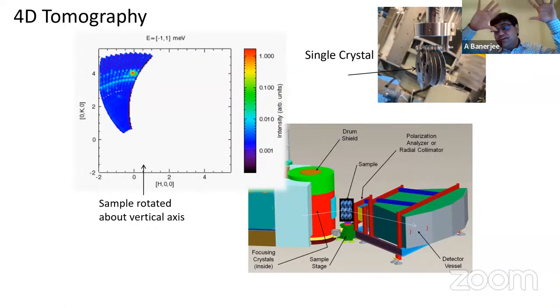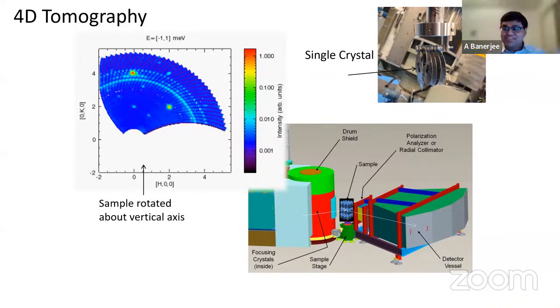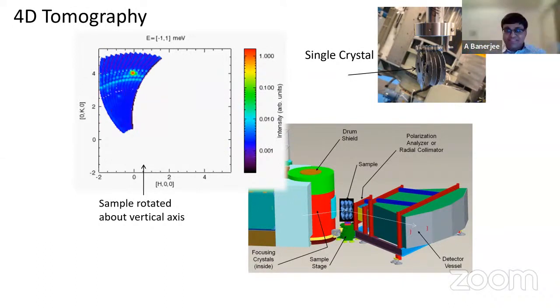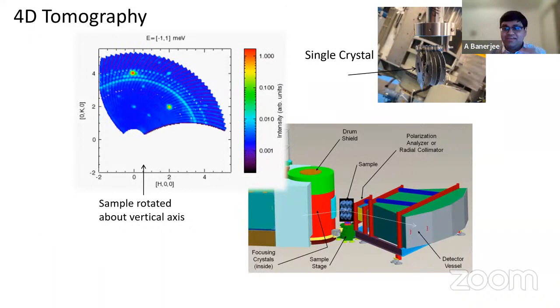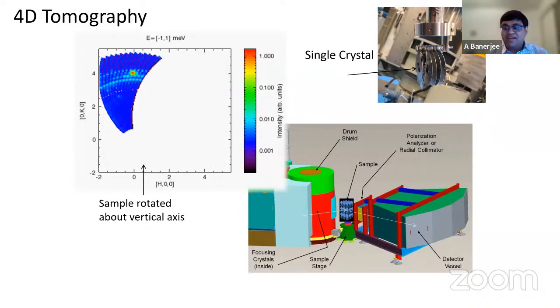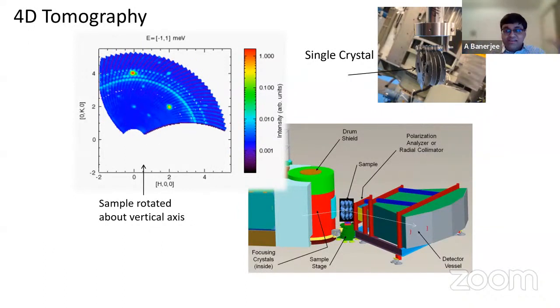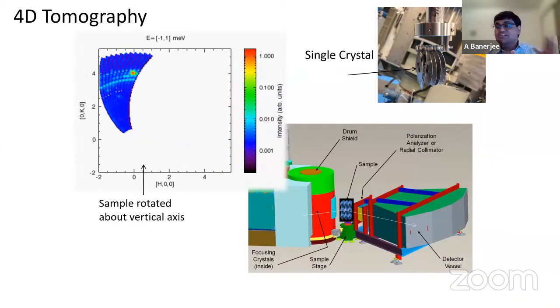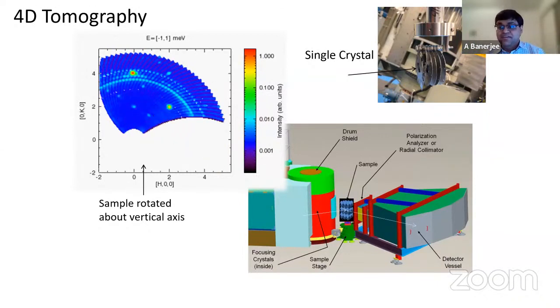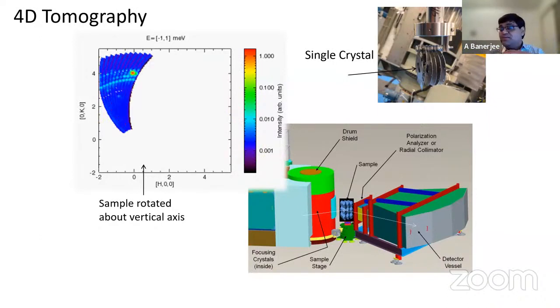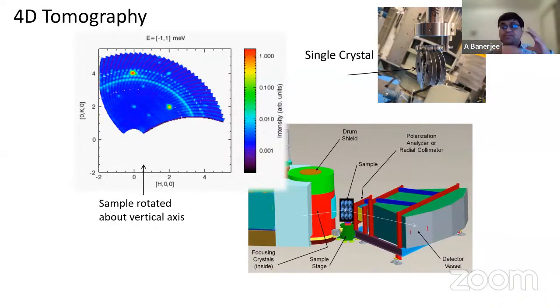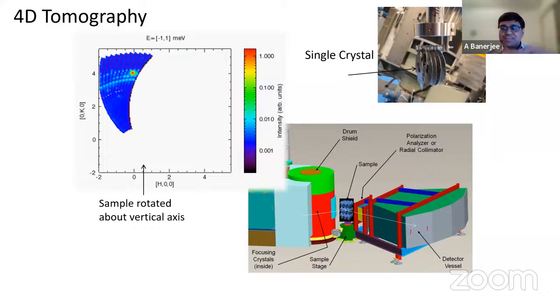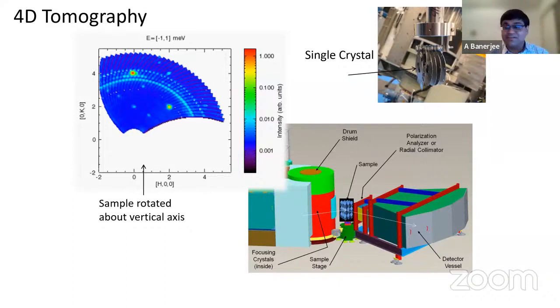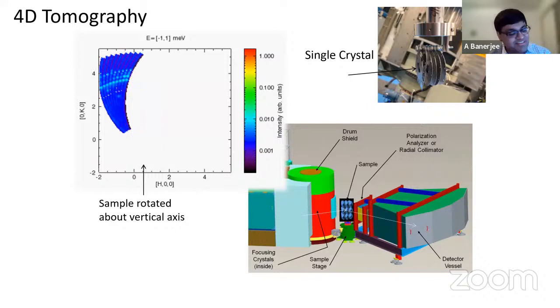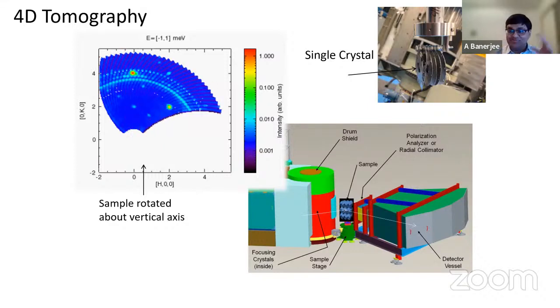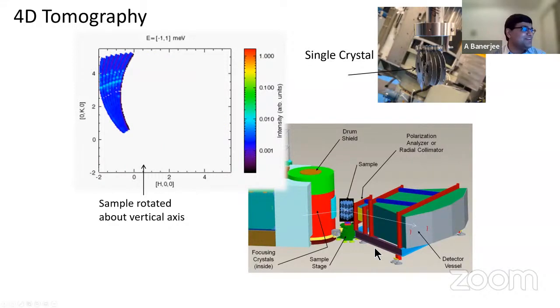we almost get 2 terabytes of data. And then we join these 2 terabytes of data into one single file where we can get all the information together. And that's how we can get the entire reciprocal space map in both space and time, in energy and momentum. And there it contains all the information of the phonons, the magnons, the spinons, and everything. So looking at 2 terabytes of data is challenging, but that is something that as neutron scientists we are trained to do, knowing where to look for the information.